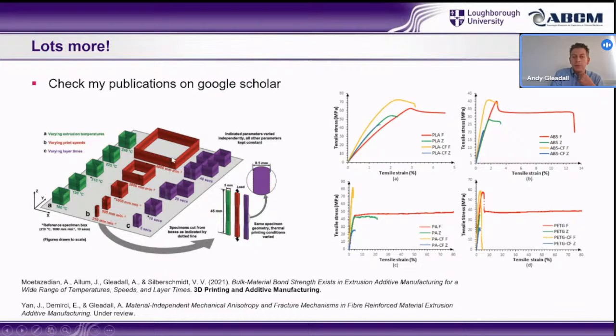This is a 16-fold increase, and with layer time changing from 5 to 40 seconds. So that's an 8-fold increase in layer time. So clearly hugely different thermal conditions, cooling and everything going on here. But the results of that study were basically finding that the bond wasn't affected. And that really gave us confidence that the interlayer bond was actually molecularly very sound. And it's just that considering the geometry is really important if you want to evaluate the mechanical properties.